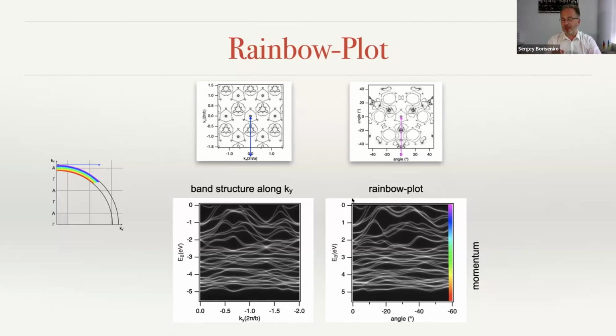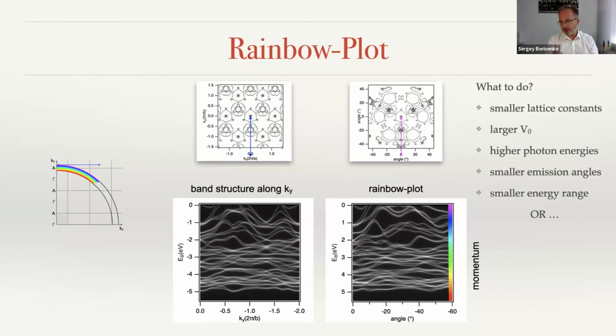A quick estimate: the typical irreducible part of the Brillouin zone is 0.5 reciprocal angstroms. If one measures with helium-1 radiation, 21.2 eV, and records the spectrum down to 5 eV, sometimes people record down to 10 eV, then by 5 eV binding energy you go through the irreducible part 2 times. So this is indeed a strong effect and has to be taken into account, especially if the material is pronouncedly three-dimensional. So what to do?